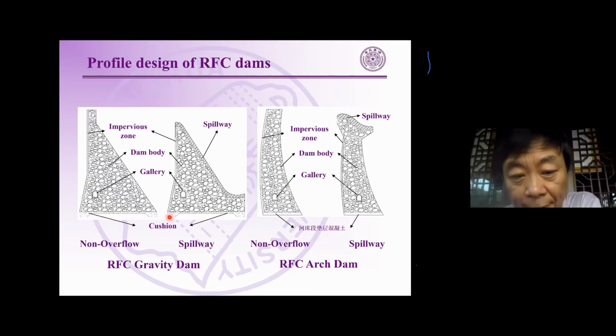And also at the bottom of the dam body, we set a conventional concrete cushion. We can also use some galleries in the dam body. Of course, for an arch dam, we can also use an impervious zone and set some galleries. And this is a non-overflow section of the gravity dam, and this is a spillway. At the spillway, we can use conventional concrete, because it is easy to build in these small regions, and most important, the concrete for the spillway has to be erosion resistant, and for that kind of erosion resistant concrete, the better choice is conventional concrete.